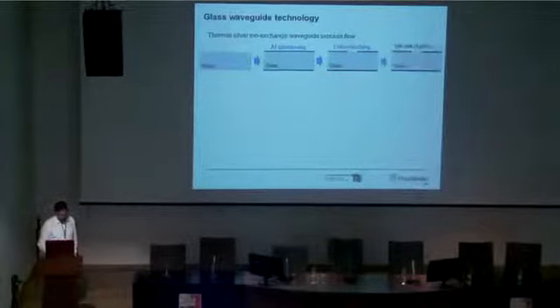So the process looks like this. We start with the glass, buying it from Schott or Corning. Then we sputter aluminium on both sides of the glass. Then we structure this aluminium using lithography and etching steps, so we have a mask opening here. Then we put this glass in a salt melt containing silver ions, and immediately ion exchange between sodium and silver starts, and we have a refractive index increase only in this opening area here.